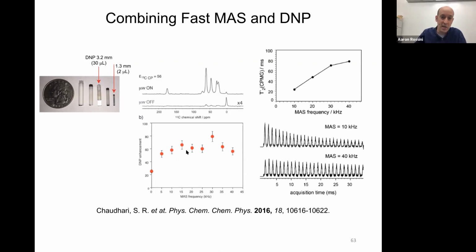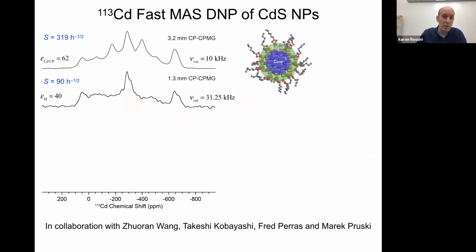Linden's group published a nice paper back in 2016 showing that enhancements don't really go down. Of course, this is on-off enhancement. This is not reflecting depolarization. But enhancements don't go down when we increase the MAS frequency. And then in some cases, you can also get increases in T2 prime. So what we've been doing in this most recent study that we're hoping to submit the manuscript soon is looking at combining fast MAS and proton detection. So I'm just showing here our 10 kilohertz cadmium-113 NMR spectrum of the cadmium sulfide and 31 kilohertz spectra obtained on a 1.3 millimeter DNP probe.